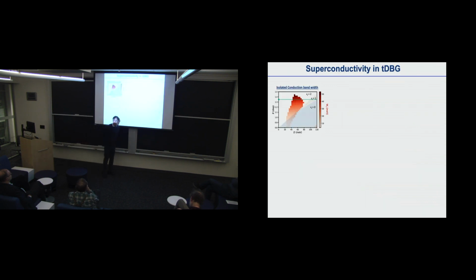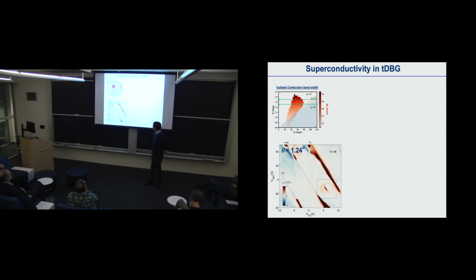We chose different angles, especially going to very small angles, which leads to slightly different Chern numbers. What we see is that similar things happen. Applying the magnetic field with displacement field, we start to stabilize this correlated insulating state at finite displacement field.